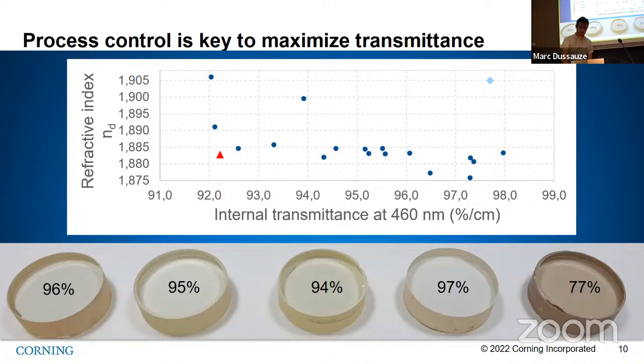And the glass we developed for AR is this one here. So first we increased the refractive index to 1.90, and then we were able to achieve in the lab internal transmittance above 97%. This glass is now in production. That's Corning's new 1.9 glass for augmented reality. And obviously, we keep on continuing to work on higher indices. So in January this year, we announced the Corning 2.0 high transmittance glass for augmented reality. And this work is a continuing story.